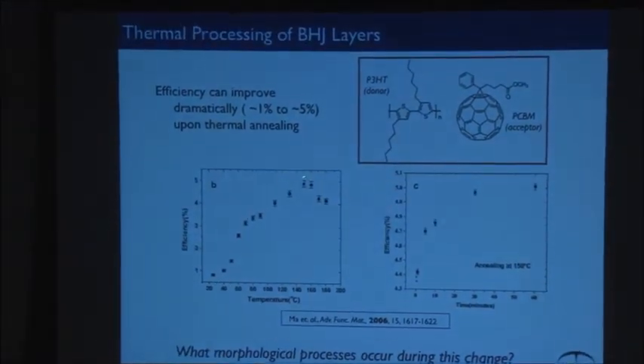What has happened is you cast these things, and the processing matters quite a bit. You spin coat these films, and you can make a solar cell with maybe 1% efficiency. But then you heat the film up, and you make another solar cell, and the efficiency goes up 5x. That's a huge factor. In solar cells, this is a huge number. You don't usually get many orders of magnitude, you get linear factors. And so you ask the question, what happened between here and here?